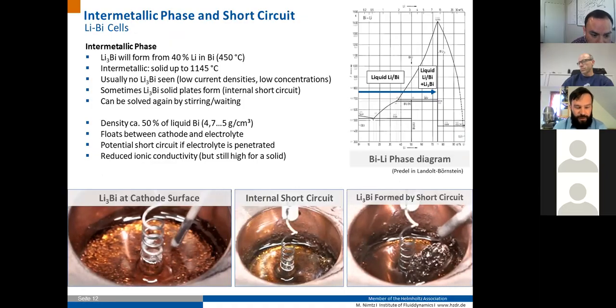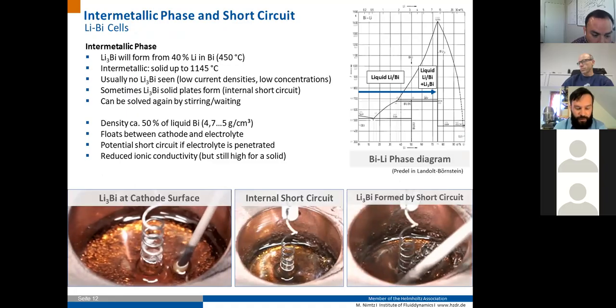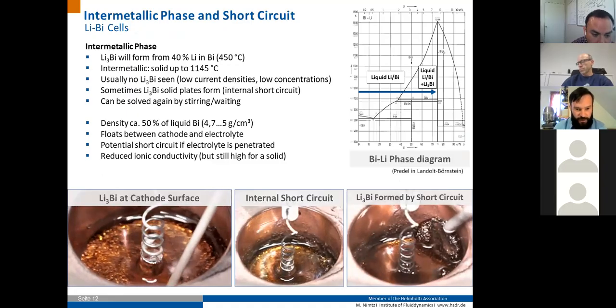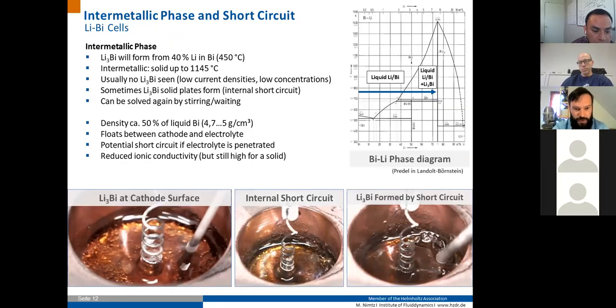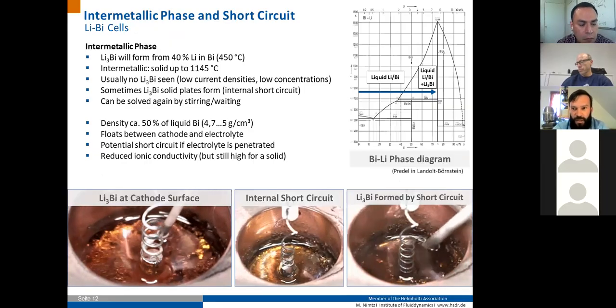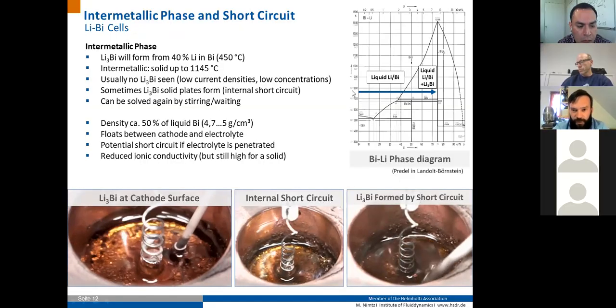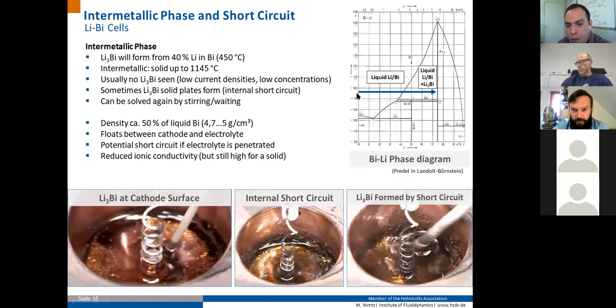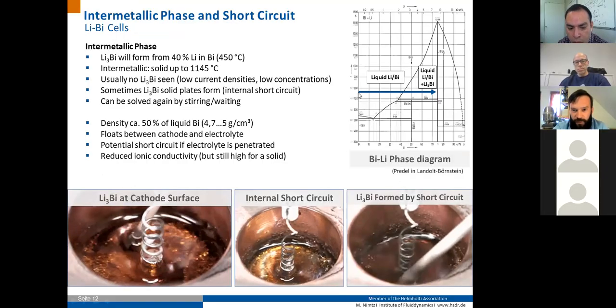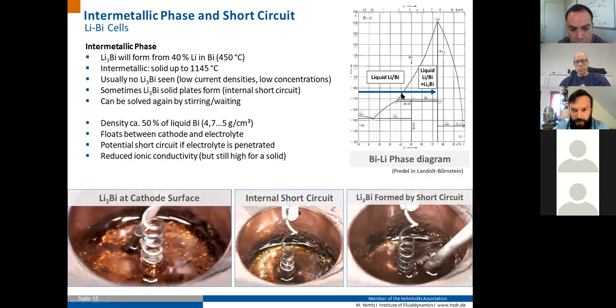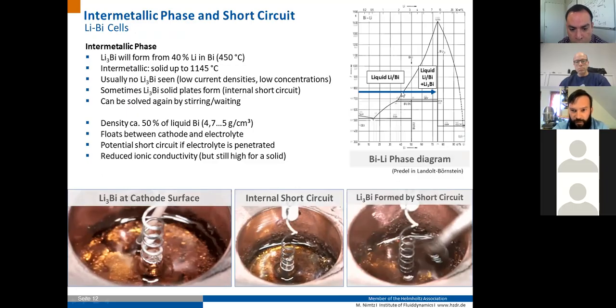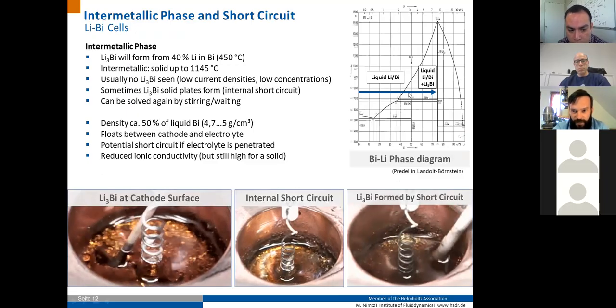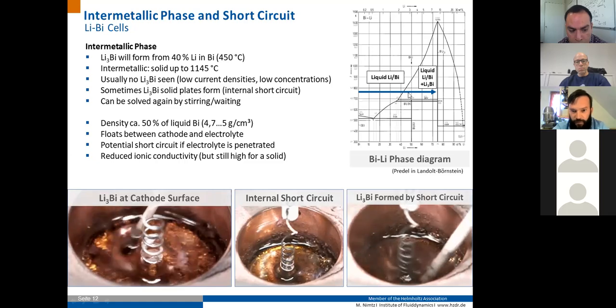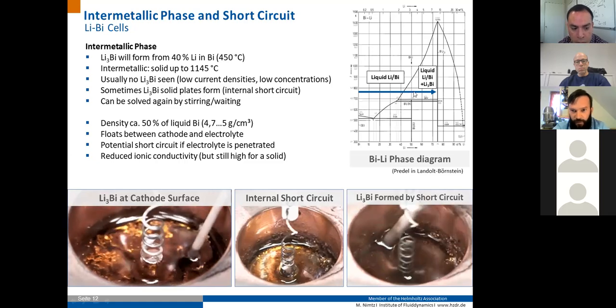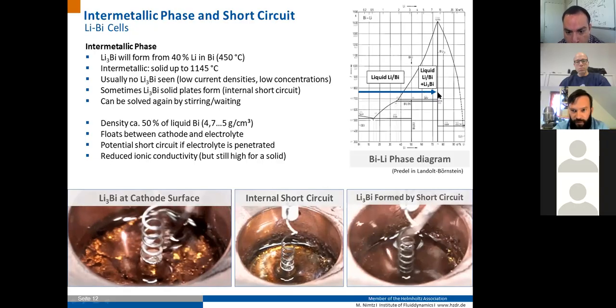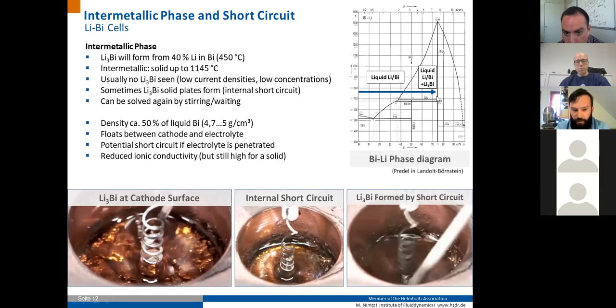One thing which you would expect during a short circuit is the formation of the intermetallic phase. If you have a look at the phase diagram, a typical discharge of a lithium bismuth cell would start at the left side of the phase diagram here across a liquidus line, and then from here the intermetallic phase would start to form, typically in form of smaller crystals, and then if you hit the intermetallic line, the whole system would be solid.